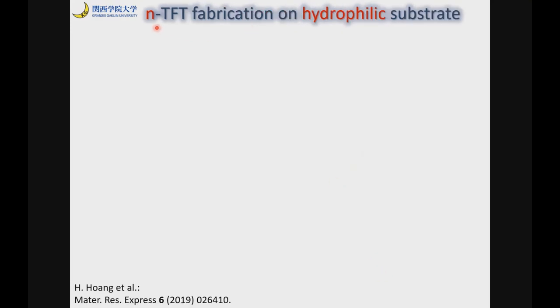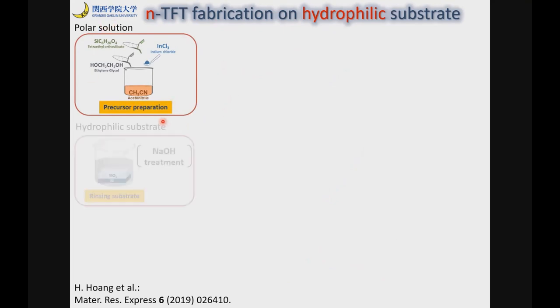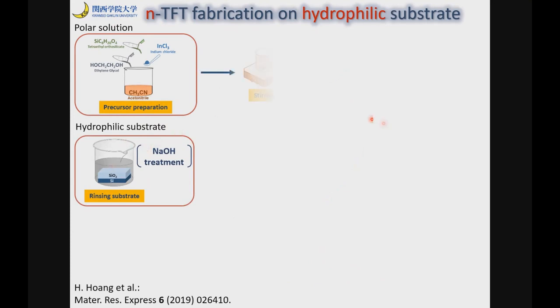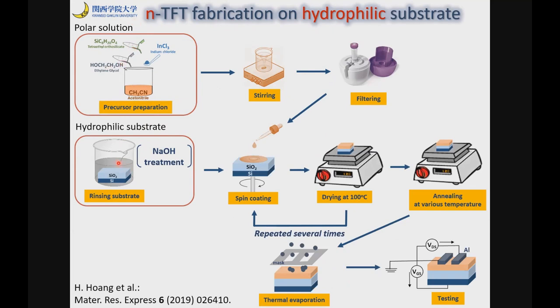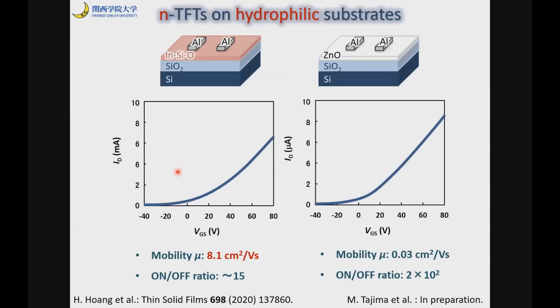Okay, next, we tried the N-type TFT fabrication on hydrophilic substrate. The process is the same, but the raw materials and the treatment are different. So we use a polar solution on hydrophilic substrate treated with NaOH. In this case, we succeeded in fabricating two types of semiconductors, the indium silicon oxide system and the zinc oxide system. In both cases, we succeeded in the operation of the TFT device. In the indium silicon oxide case, mobility is very close to the requirement of 10, but the on-off ratios are very small. In the zinc oxide case, the mobility and the on-off ratio are much, much smaller than the requirement. These are the highest values currently obtained.